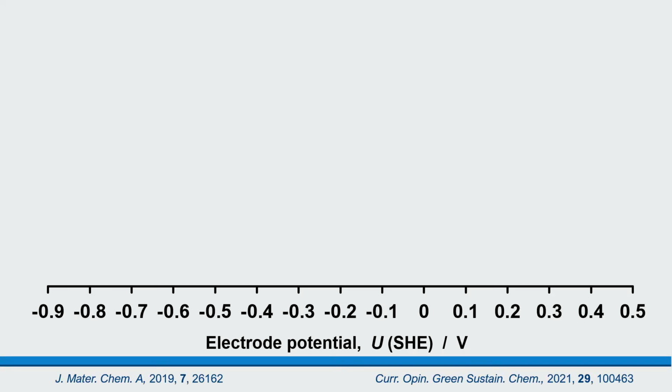One of the stumbling blocks we hit when we did our models was the identification of the flat band potential of our electrodes. So the flat band potential is an extremely important interfacial parameter. It's a reference state relative to which photoelectrochemical kinetics may be assessed. But the assumptions made during flat band potential determination from various measurements, including interfacial capacitance, have led to an implausibly wide range of values being reported for essentially the same material.